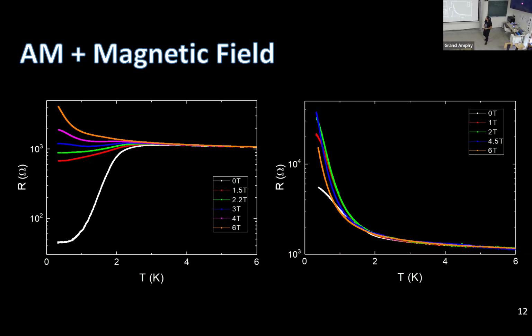So when we added magnetic field to this mix, we see that this anomalous metallic phase disappears. We go back to a normal insulating behavior. We don't see the saturation anymore. Of course, gradually the resistance increases up to a point when it's disappearing, as well as in our M2 sample. The saturation disappeared.